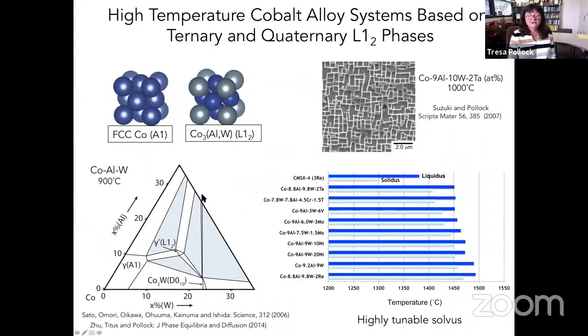Okay, so with regard to getting high strength alloys that can be printed with columnar grain structures without cracking, we've been working on a new class of materials, cobalt-based alloys. And I show here the structure of one of the early simple ones. And the motivation for this class of alloys is that they're two-phase. We have an FCC cobalt matrix and an L12 precipitate structure here, and the precipitates provide strengthening at high temperature.